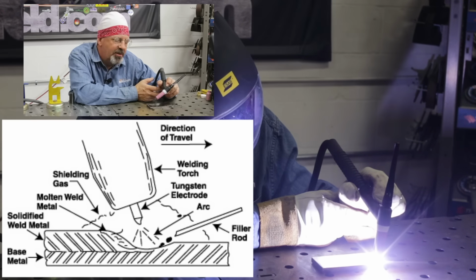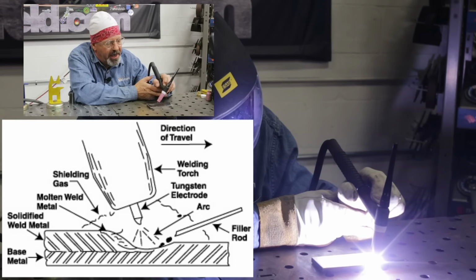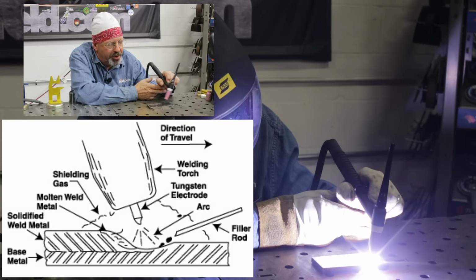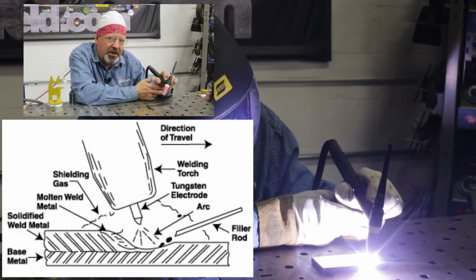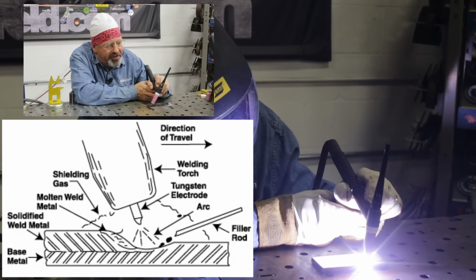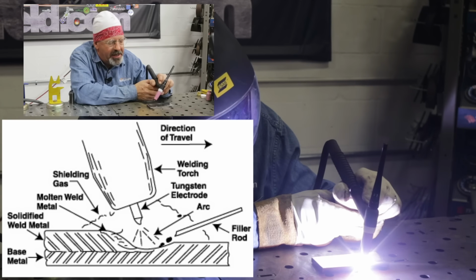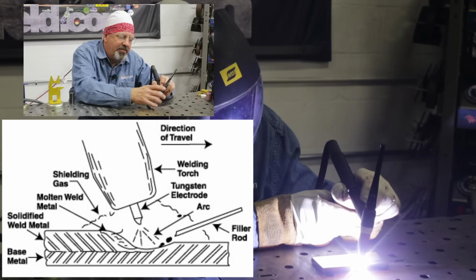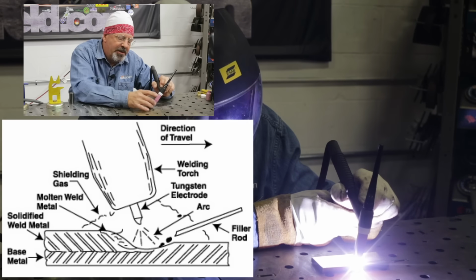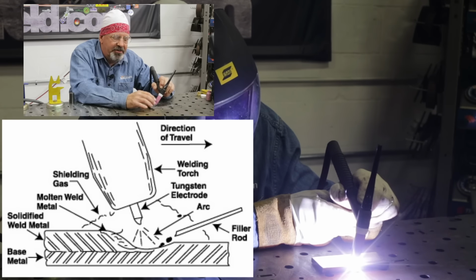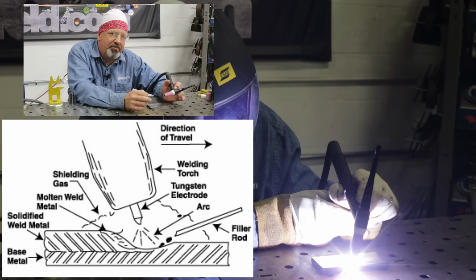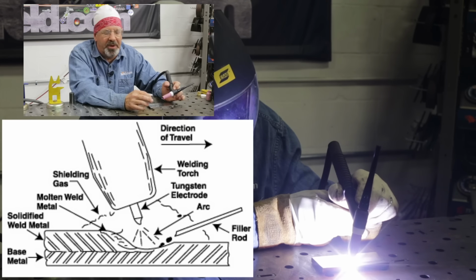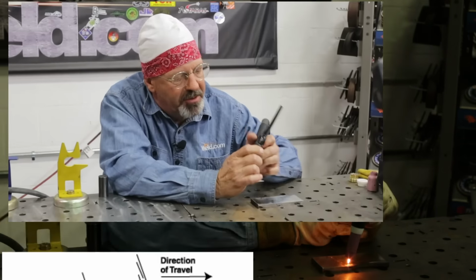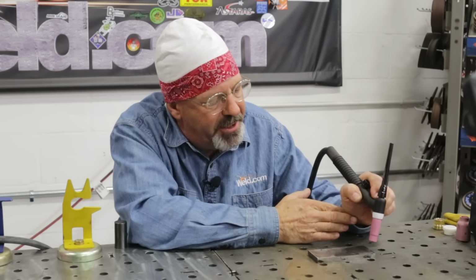With MIG welding and stick welding, there's a drag angle or a push angle. This is a push angle at all times. If you try to drag TIG, sometimes you'll get a Venturi effect. You get an air pocket that gets introduced in here and you create porosity. Porosity is bug holes in your weld. It's not fun. So this is always a forward angle.